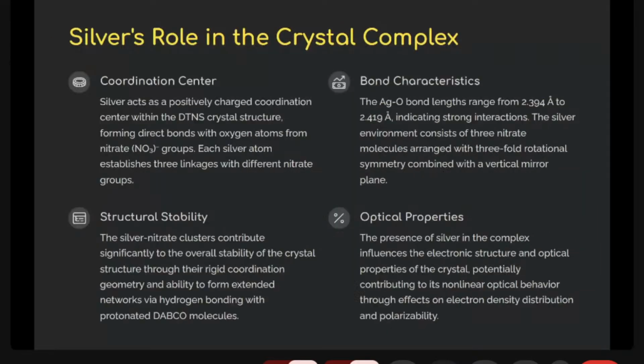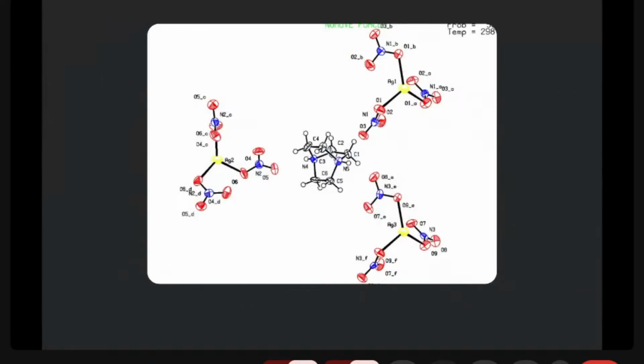Now, what is the role of the silver in that case? Here you can see the Ag1, Ag2, and Ag3. The silver-oxygen bond length is about 2.3 to 2.4 Angstrom, reflecting strong ionic and partially covalent interaction. This bond distance is a clear indication that silver does not merely sit idly, it actively participates in anchoring the crystal framework. Additionally, the geometrical arrangement around the silver displays threefold rotational symmetry. In P3c1, the 3 is the rotational symmetry combined with the vertical mirror plane. This level of symmetry is critical. It contributes to the non-centrosymmetric nature of the DTNS crystal.